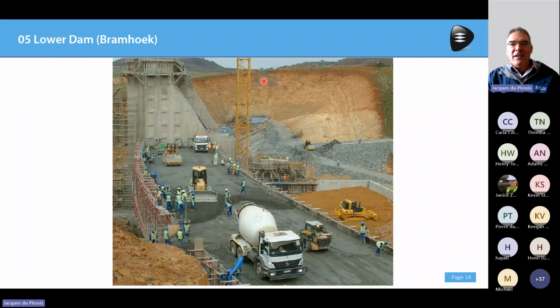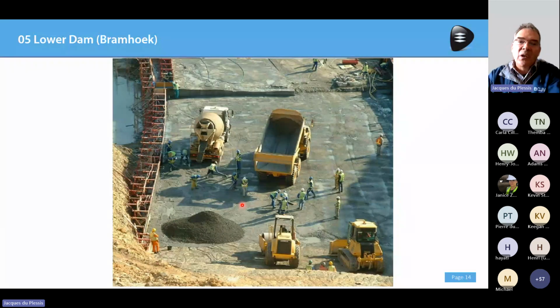Then let's go to the lower dam, Bramhoek Dam. It's an RCC dam, so completely different to the upper dam. So for those of you that are not familiar with RCC, it's roller compacted concrete that you bring in, but you treat it like earthfill. So you would bring it in with a dump truck, dump it, spread it with a dozer in 250 millimeter layers approximately, and then you compact it with a roller.